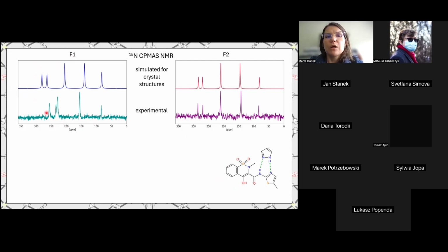So we need to resolve this puzzle, and actually the only signal that matches here is this methylated nitrogen from meloxicam, and all the rest of the nitrogen atoms chemical shifts are very much off. So we immediately assumed that this is because of the protonation state of those molecules, that something has to happen here.